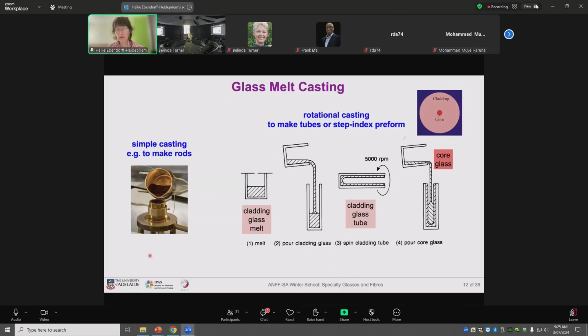So now I go through a few of the preform fabrication techniques. I mentioned the glass melt casting technique. This is what we use at Optofab Adelaide. And recently for the special ZBLAN fluoride glass, which was indeed then drawn in space, I talk about this later on, we use the rotational casting to make the preforms.